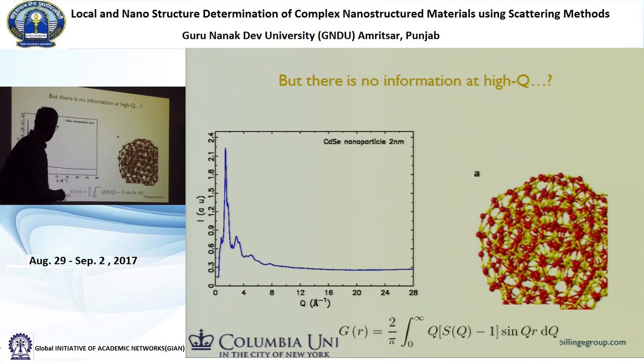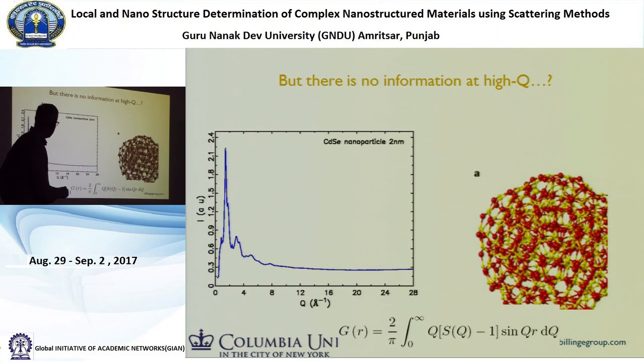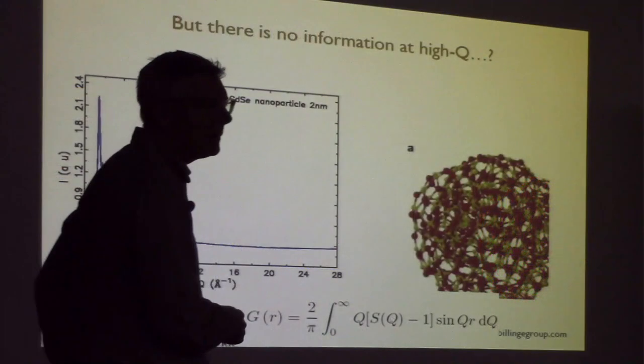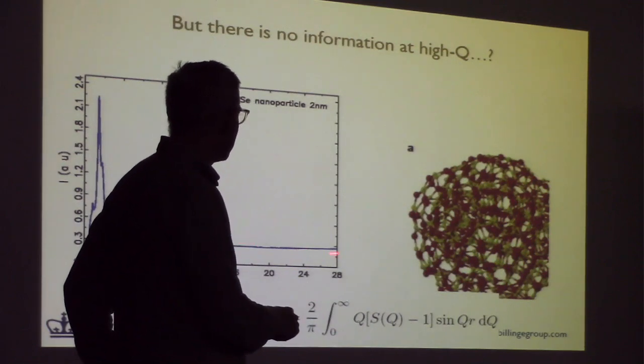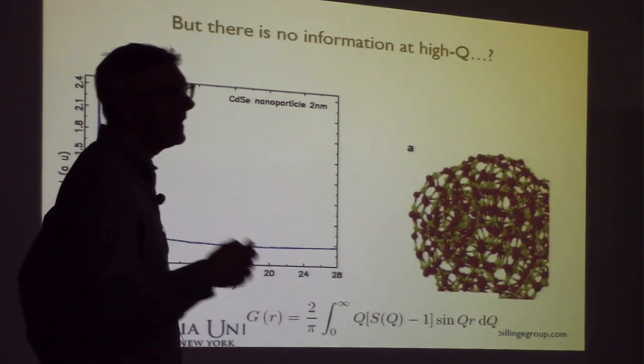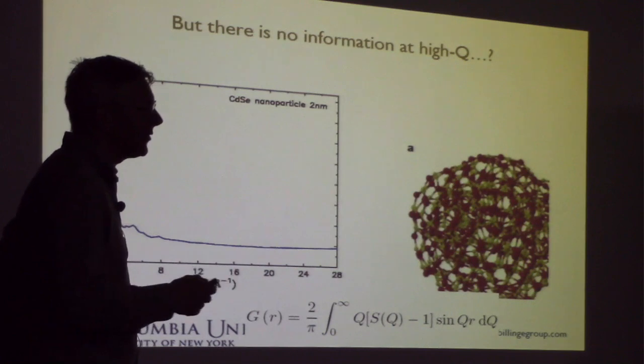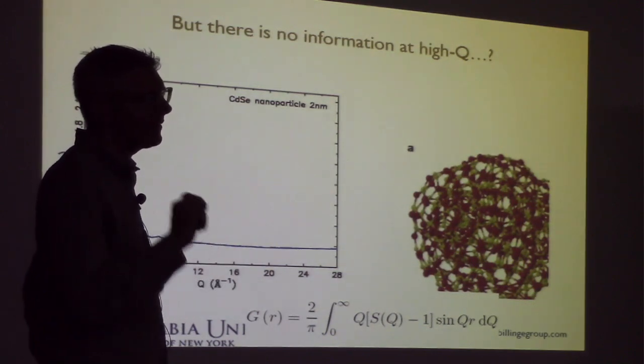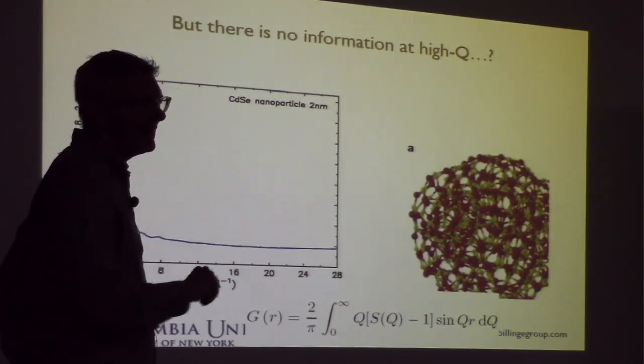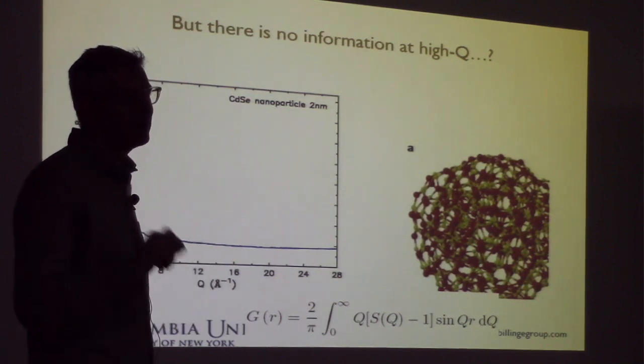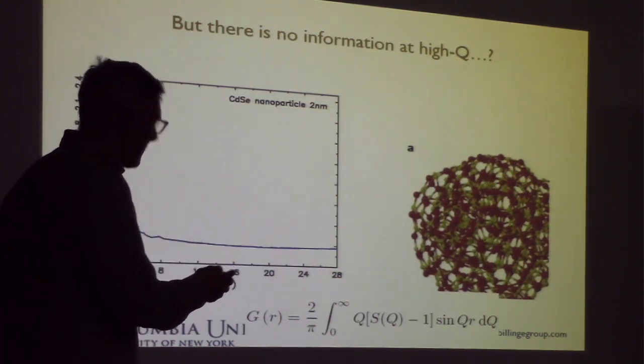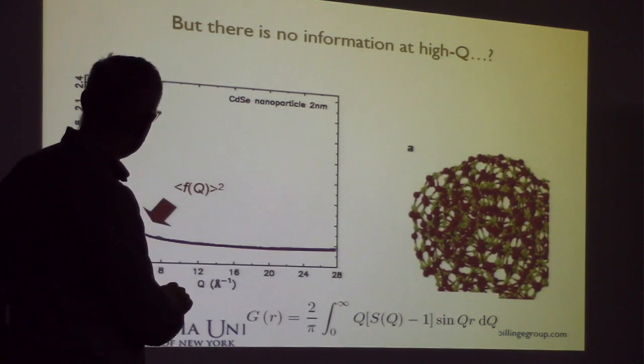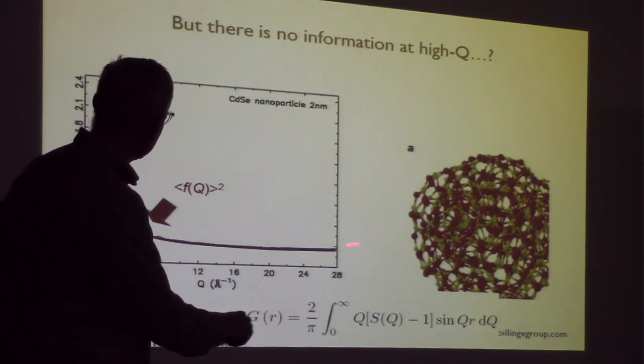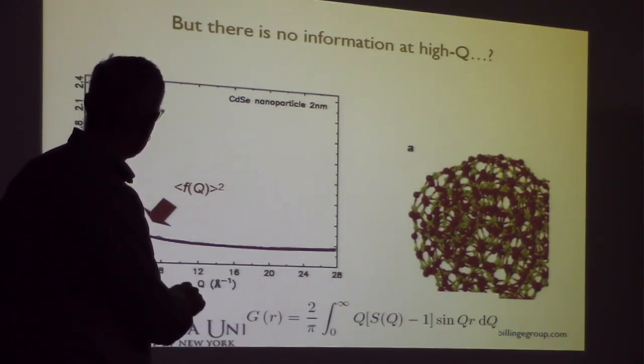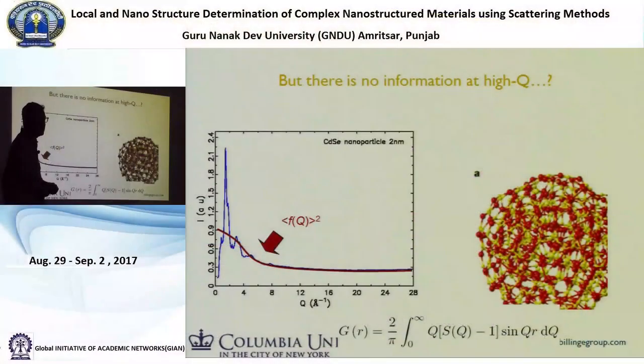But what you see is that we measured over a very wide range of Q. Nothing is happening. So why did we do that? Why did we spend so much time measuring nothing? Now, one of the normalization steps during the data processing is you divide by the scattering cross-section of the sample. The scattering cross-section of the sample is the square of the atomic form factor. So the atomic form factor looks like this. It's a very smoothly varying function like that. And so we're going to divide the blue by the red curve.